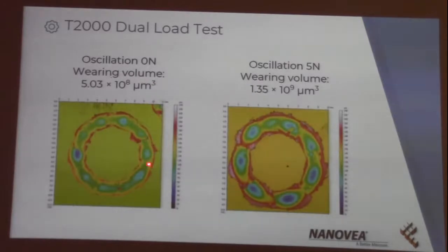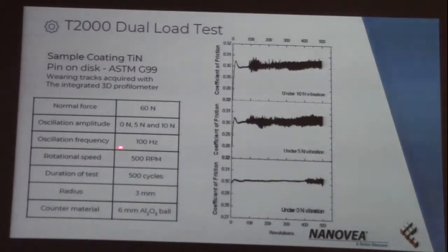This can be very interesting because we can see that at some point, even if TiN is quite an appropriate material, there are some areas that are more stressed by the test, and in the case of superimposed 5 Newton oscillation, even if the oscillation period is not the same as the frequency of the motor, these are mainly due to the material properties or non-isotropic material properties, and we can see the difference in behavior. We can imagine using this kind of test in a case in which, for example, in an airplane, we have a superimposed vibration due to the whole system that occurs during the life of the material. And this is another test.